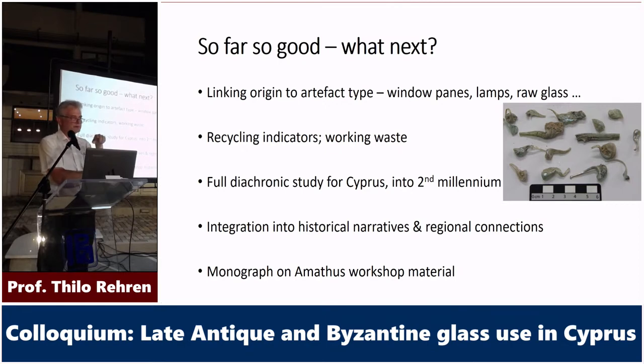In a previous study with colleagues Fatma Mari'i from Jordan and others, when I was still in London, we looked at glass from Petra and from Deir en Abata, a pilgrimage site in Jordan, both Byzantine, but very nicely differentiated. The big Petra church was very homogeneous Levantine glass, very flashy building, all more or less one big event of creating, while that little monastery in Deir en Abata had a much more mixed origin of glass, with a lot of Egyptian glass coming in, which one could envisage and link to the historically known Egyptian pilgrims coming to that site where the salt statue of Lot has been commemorated.